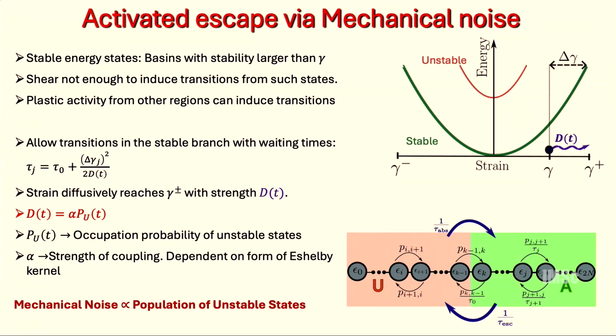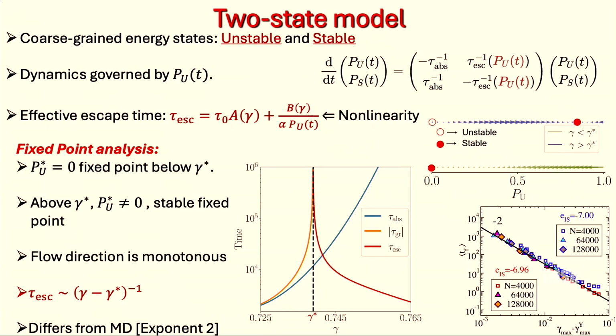So here, just for concreteness, I have all my energy states, and for a given strain amplitude, this is the boundary between stable and unstable states. And I'm going to ask what is the probability for the system to be in the unstable states, and that probability is going to determine the diffusion coefficient that I will have, which will allow me to escape out of the absorbing states. So we can have that picture and write a two-state description where I write the master equation for the probability to be in the unstable and the stable states, and without going into any detail because I'm running short of time,